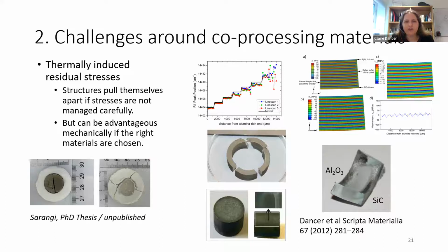Another challenge with co-processing materials I struck on earlier has to do with these thermally induced residual stresses. If you make a material which contains materials with quite different mechanical coefficients of thermal expansion, for example, you find that at the temperature you process it at, it's all fine, but when you cool it down, those differences in thermal expansion coefficient can pull the sample apart.